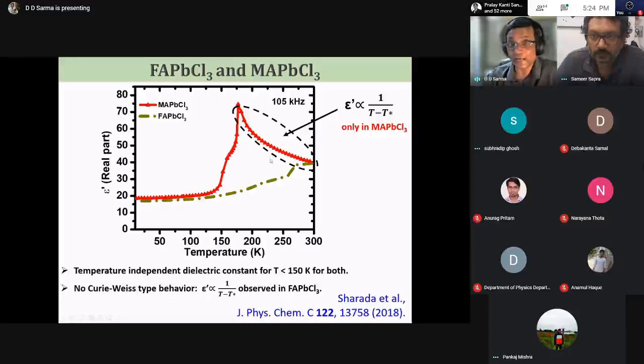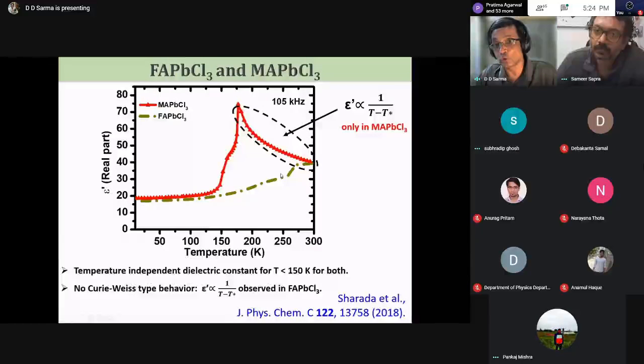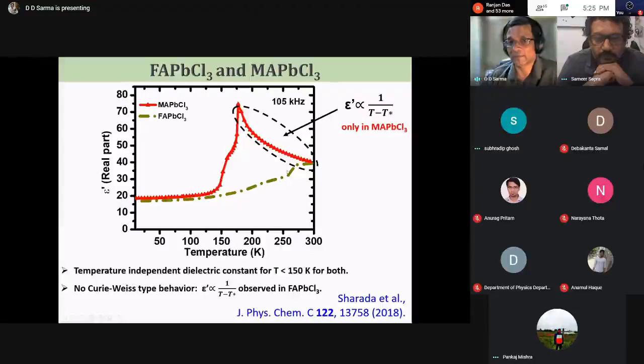In this particular paper we had wrongly interpreted, saying that maybe FA is not rotating because we didn't see this response. But later we understood that MA has a dipole moment which is 10 times larger than FA. This is about 1 D and this is about 0.1 D. The proportionality constant is the square of the dipole moment, so the contribution from MA to FA is 100:1. That's why you don't see evidence of dipole here, and what you're essentially seeing is a non-dipolar contribution to the dielectric constant in FA.